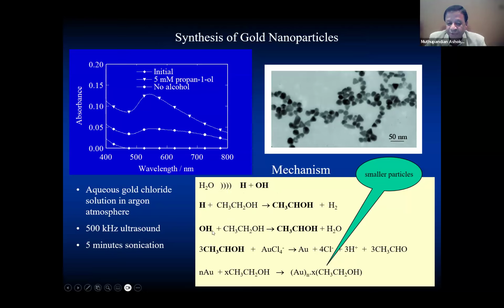So by knowing a little bit of chemistry, I can convert the oxidizing radical into a reducing radical. That way I can increase the overall rate of formation of gold. So you can see that compared to water, when I have alcohol, I have a higher amount of gold produced. So I can play some chemistry here also. I can use my chemistry knowledge to produce some gold particles.